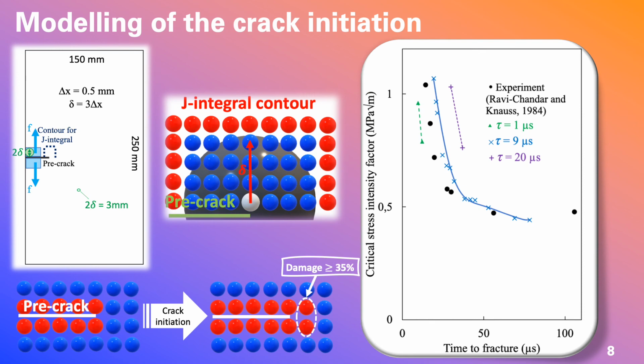The force boundary conditions were applied to the portion of the crack surfaces in the width of 2 horizons, leaving the near-tip fracture surfaces free for the J integral calculation. Stress intensity factor was calculated using dynamic J integral approach, drawing a contour around the current location of the crack tip, so that only the neighborhood of the particle located at the crack tip is placed inside the contour of J integral. Crack initiation was considered at the moment when in the next element after the crack tip the damage of at least 35% was achieved.